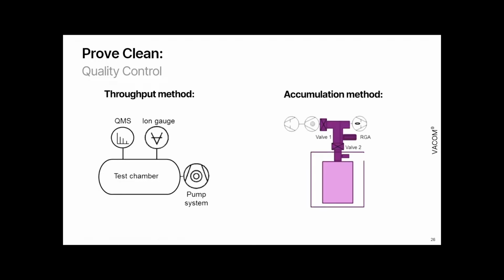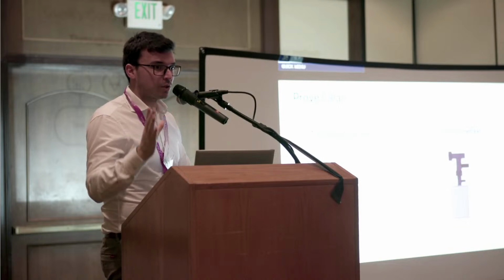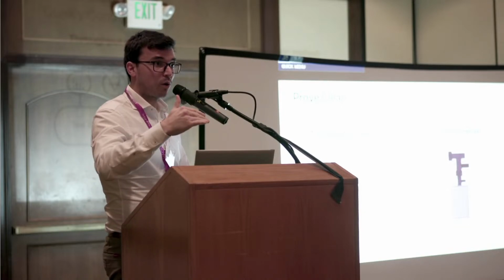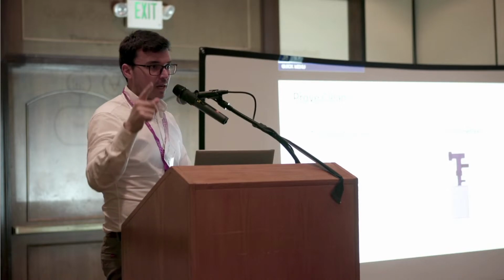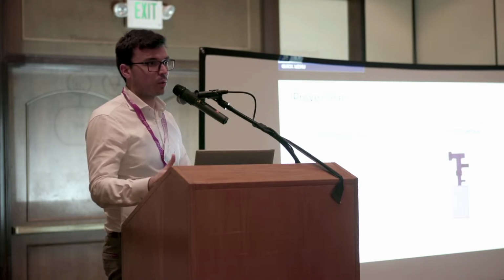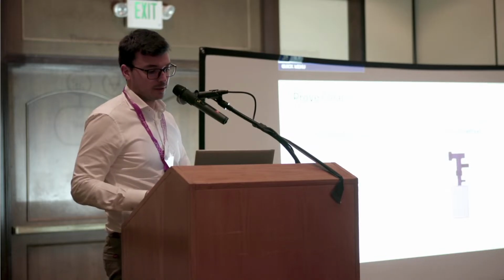That gives you the contamination on your part. So if the parts are too small, we use something called the accumulation method, where we enclose a part in a separate chamber, close it off, then have another reference chamber which is being pumped down, which is connected to an RGA. Then once a certain time has passed, you can open the valve and you will see an increase in pressure in that one chamber, and you will be able to get a spectrum so you can actually see, okay, what's the contamination on this very small part.